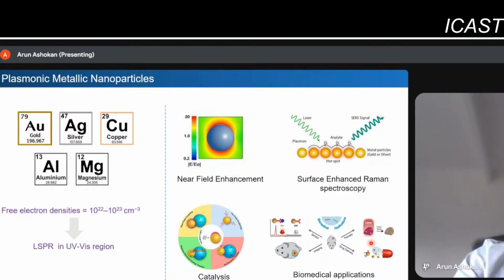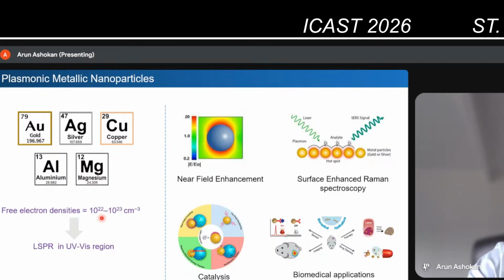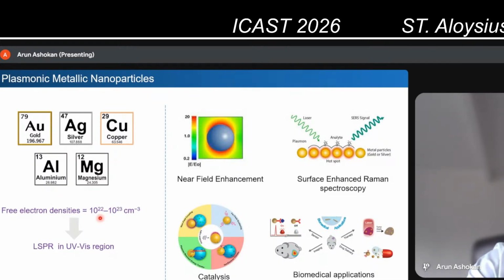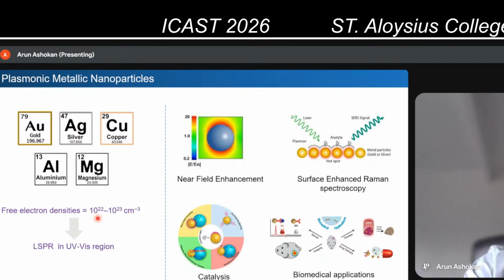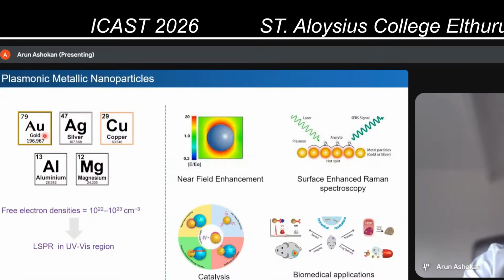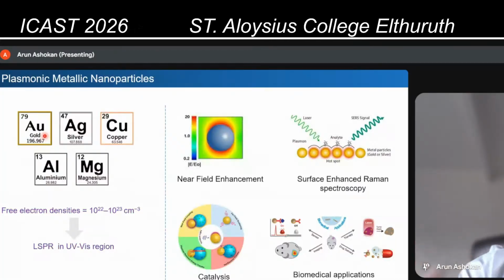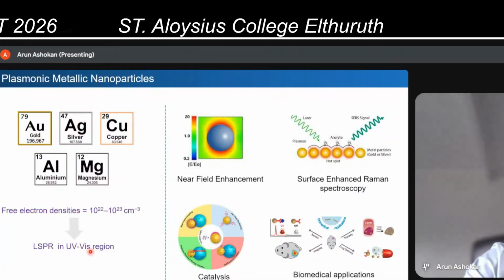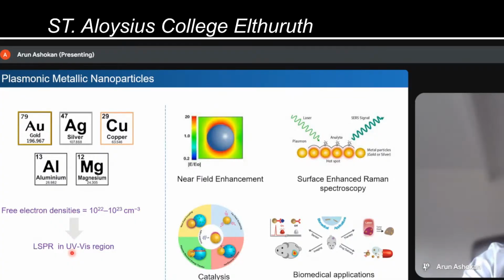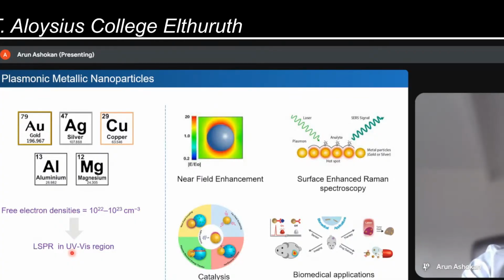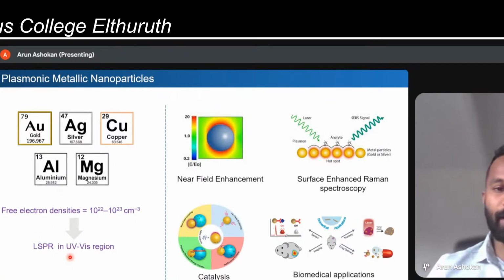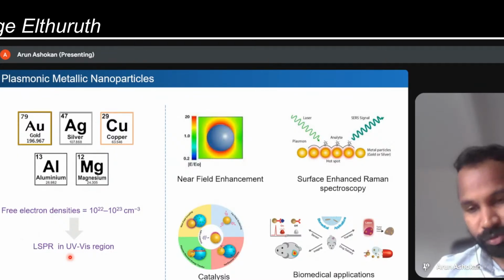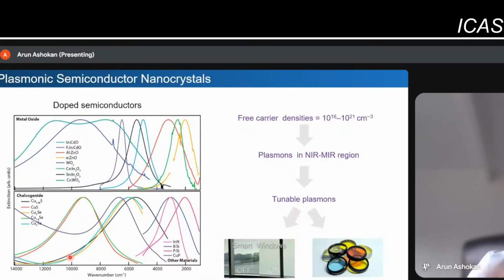The problem here is that we have metals, and they have some free electron density, as I said. And this is the maximum you can achieve with these metallic particles. You can't easily change the free electron density in a metal, and you only get the surface plasmon in the visible and UV range. So we want to find materials which we can also use in the near infrared. I'll tell you the reason why in the next slide. As I said, I will be speaking about plasmonic semiconductor nanocrystals.